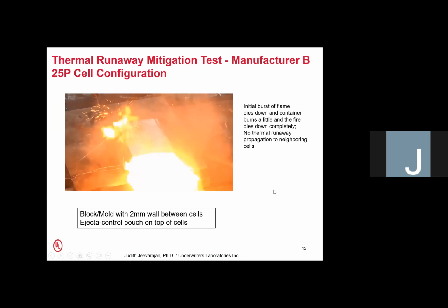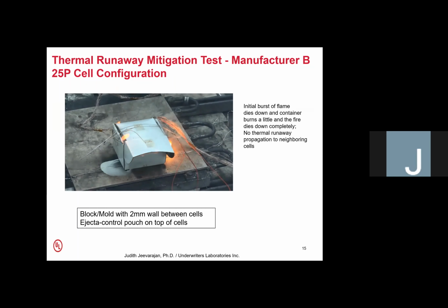What you will see here is that there's an initial burst of flame that actually dies down, and then the container, as I said, is not UN rated, so the container starts burning, and even the container after a little while stops burning. And we found that there was no thermal runaway propagation in this case, as I showed in the previous chart. So you'll see that it just dies down. I've just reduced the video for the sake of time to show you just the parts that are interesting. As you can see, even though there's a fire in the box, the cells do not contribute further to that, and they're not affected by it either.